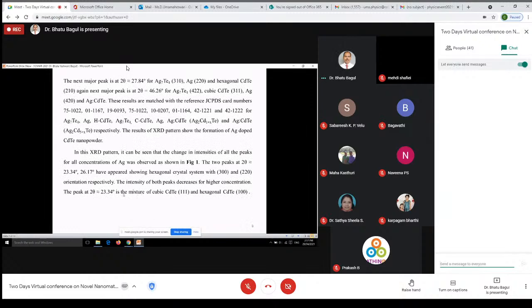In this pattern also, we can see that the results match the references with the JCPDS data cards. This is the JCPDS data card for Ag7Te4, for hexagonal CdTe, cubic CdTe, Ag and Ag doped CdTe. Therefore, the results of the XRD pattern show the formation of Ag doped CdTe nanopowders.